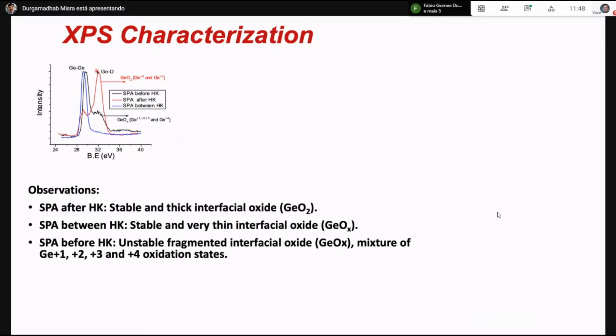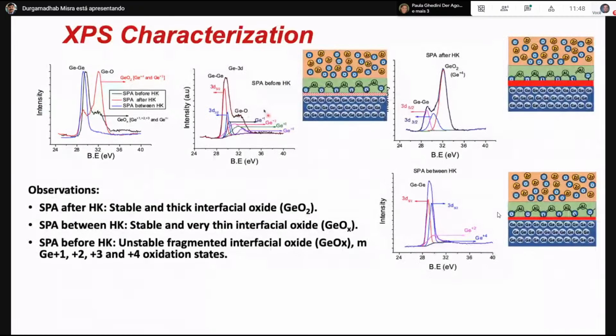Then we found out that germanium oxide is being formed. In the three different cases, the germanium oxide before the high K deposition was not of high quality, whereas the germanium oxide after the high K deposition came out to be pretty good quality. And this is because of the SPA. It creates a stable suboxide, not a germanium oxide completely. And that helped to bring down the interface state density and also gave high quality and better EOT. So those are the things.